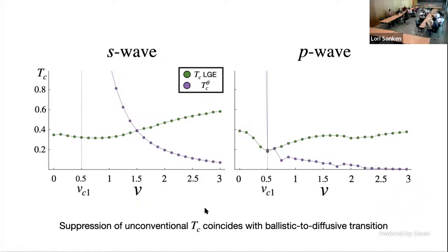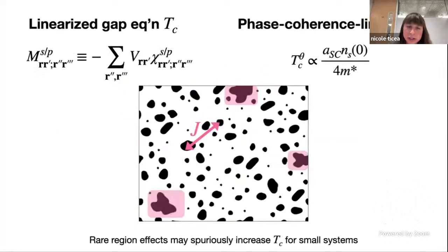And the answer to the question of why you would expect the phase stiffness to be very high for small amounts of quasi-periodicity is that if I have very low quasi-periodicity, then the condensate is quite spatially homogeneous. I don't have a picture, it's in my supplement, but it ends up being quite spatially homogeneous. So then you don't really have this granular picture at all, and it's easy for your phases to be aligned.